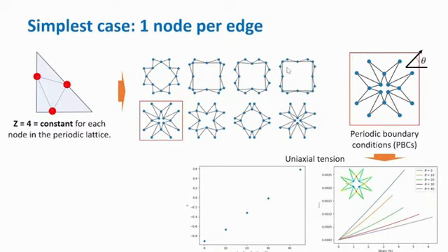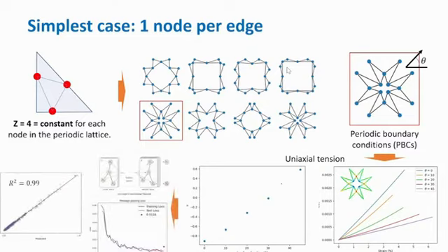This is an example in one unit cell, and you can see that, for example, in this plot, we obtain a huge range for the Poisson's ratio, ranging from minus 0.85 to 0.6. Then we wanted to predict the Poisson's ratio in this case using graph neural networks, which is the first time that someone is performing this task.